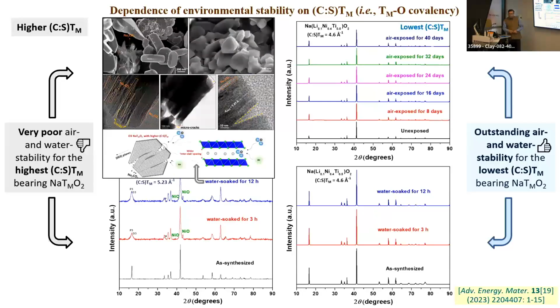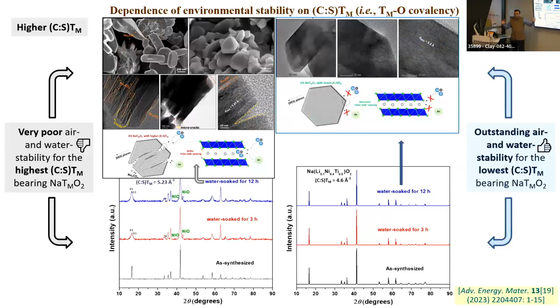If we look at the TEM image after water soaking for 12 hours, as expected, the structure looks totally damaged, whereas this looks perfectly intact, as if it was just in the glove box. But no, it was soaked in water for 12 hours, then the TEM was done, and it looks perfectly intact. So it kind of proves the hypothesis that when we have a low charge to size ratio of my cation combination in the transition metal layer, the air-water stability is much better compared to the other way around.